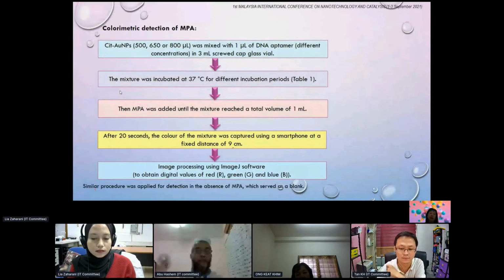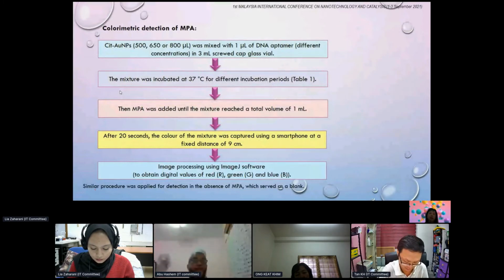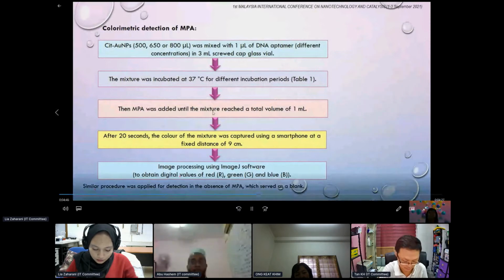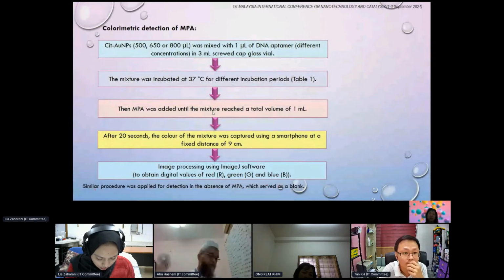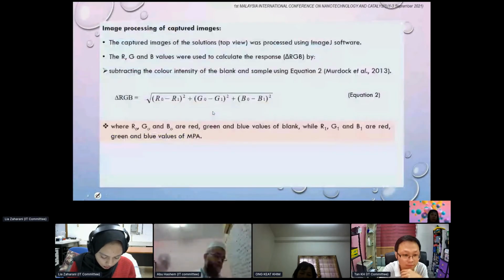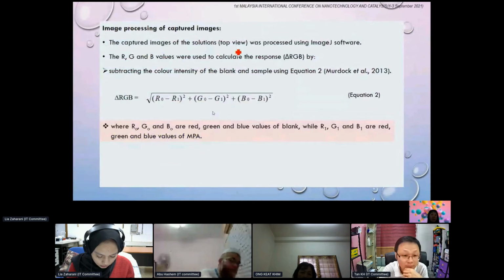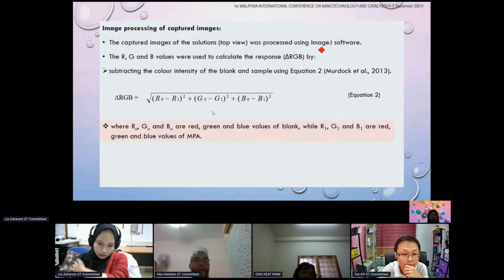After 20 seconds, the color of the mixture was captured using a smartphone at a fixed distance of 9 cm. The captured image was processed using ImageJ software to obtain digital values of red, green, and blue. A similar procedure was applied for detection in the absence of MPA, which served as a blank. The captured image of the solution top view was processed using ImageJ software as I mentioned just now.